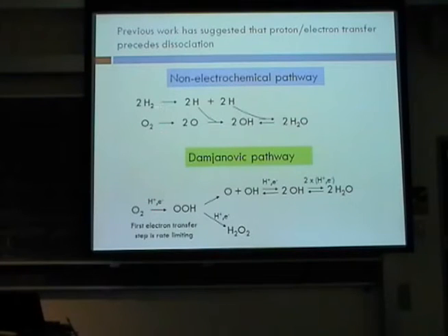system, instead of having hydrogen being added during the oxygen reduction reaction, you have proton and electron pairs that are coming from different places, remember. The electron's going through that external circuit, the proton's coming through the membrane, coming through the electrolyte. And they form this peroxy intermediate, OOH. Right, and then that peroxy intermediate subsequently dissociates.